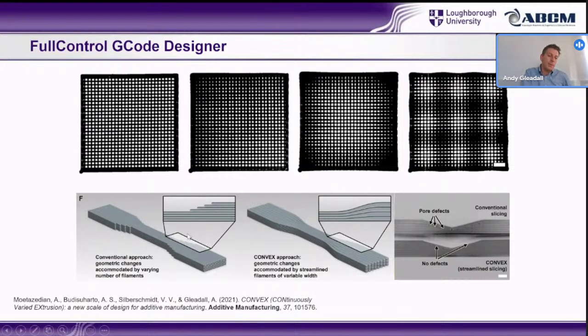And taking that towards the mechanical properties research, with our dog bone testing, we were noticing that there were defects at the transition from wide section to narrow. And here you can see the defects are kind of shoulder junctions. Often you'd have a perimeter printed, and then these steps would actually be internal, and they'd lead to stress concentrations and pores, which lead to failure, not in the gauge section, but in the transition from the wide to narrow sections.